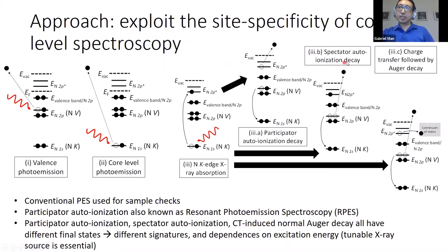In the second case, it's a spectator autoionization decay, where the core excited electron just sort of spectates and shifts the energy of the normal Auger-like decay up, perhaps by a few eV. Still a normal decay, still a localized decay. In the third type, this is normal Auger decay, but it follows resonant excitation. That means the core excited electron must have gone somewhere else, like delocalized into the surrounding matrix. All three mechanisms have different final states and hence different signatures, and different dependencies on the excitation energy. For example, normal Auger does not depend on the excitation energy, so we can use that fact to differentiate between all three mechanisms.